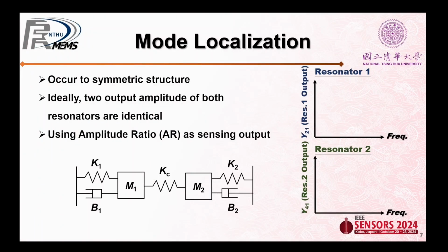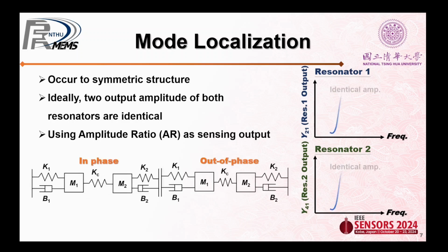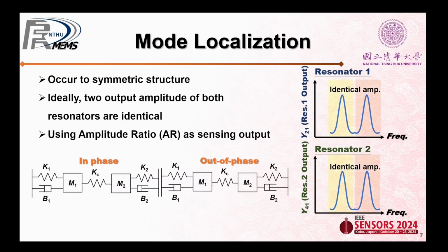Lastly, mode localization is a vibration phenomenon that occurs in a 2-degree of freedom system. After solving the motional equation, we obtain 2 eigenvalues representing 2 resonant frequencies. Each resonator has these 2 modes, and their amplitudes are identical if they exhibit ideal symmetry. Unlike typical sensors that focus on frequency shift, mode localization uses the output amplitude ratio, AR, between the two resonators as the sensing metric. So there are two amplitude ratios, AR1 and AR2, corresponding to the two modes. When the symmetry is disrupted, the output amplitude ratio changes dramatically.